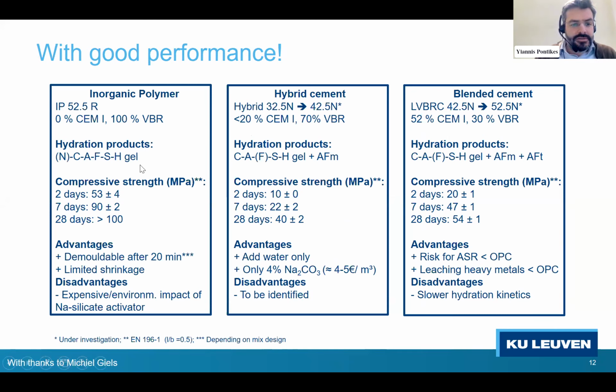So in the first case, you can see here the performance. I think most people will be asking about that. At 28 days, more than 100 megapascal, at 2 days plus 50, at 7 days about 90. Hybrid cements, depending on your mix design, but anyway at 28 days still very, very decent. I would say 40 megapascal. In terms of environmental footprint this is the best, and in terms of cost also.